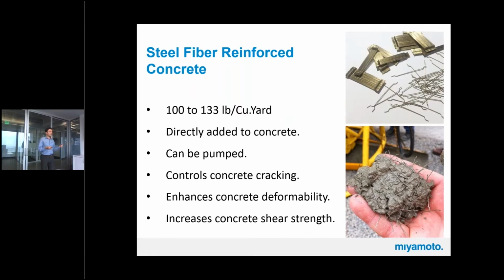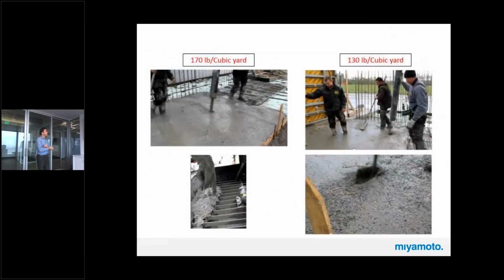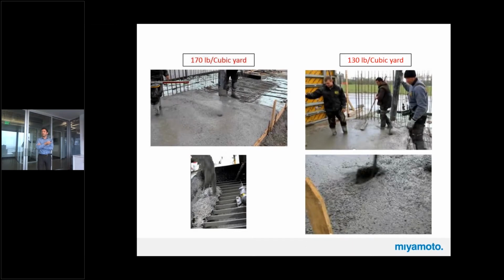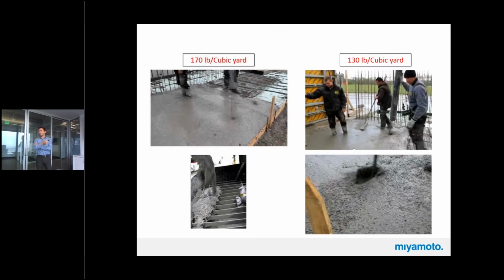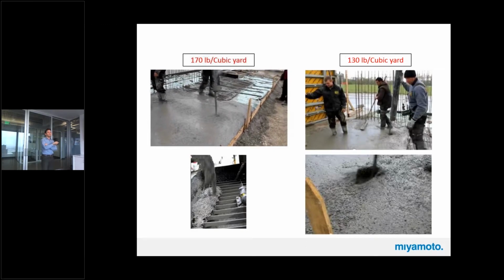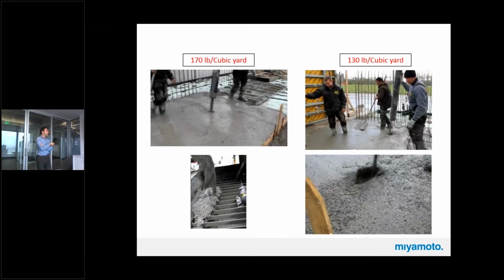These steel fibers are directly added to the concrete on site and can be pumped. That's one of the major concerns of the contractor. They can control the cracking in the shear walls, enhance the concrete deformability, and at the same time increase concrete shear strength. So here you can see how 170 pound and 130 pound fiber per cubic yard looks like. It is flowable, workable, pumpable, and you see that there's a high density of reinforcement there, so it's constructible.